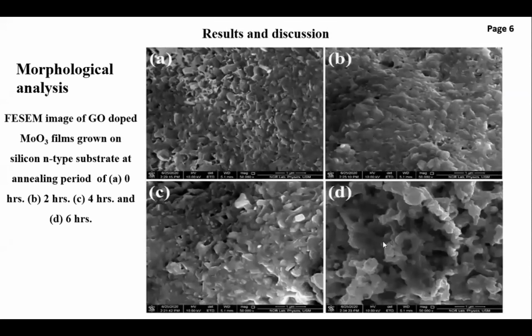Morphological analysis. The morphological result has been displayed as a function of annealing period from 2 hours to 6 hours. A refers to the morphology of the film without annealing, as deposited. B is annealed at 2 hours, C 4 hours, and D 6 hours. As we can see, the film's properties change with change in the annealing period.